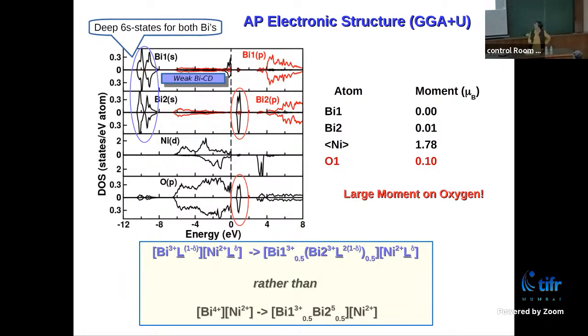And this is seen in the calculated moment, because oxygen, which should have been non-magnetic, actually acquires a large moment. So therefore, our conclusion is that in this ambient pressure phase, this compound is not really like bismuth 3+ and bismuth 5+. Rather, all of them are bismuth 3+. One bismuth has no ligand hole and another bismuth has two ligand holes. Very much like the nickel story I was trying to tell you. And the nickel, of course, remains as nickel 2+.